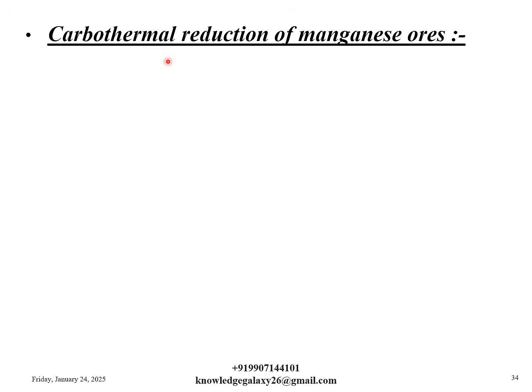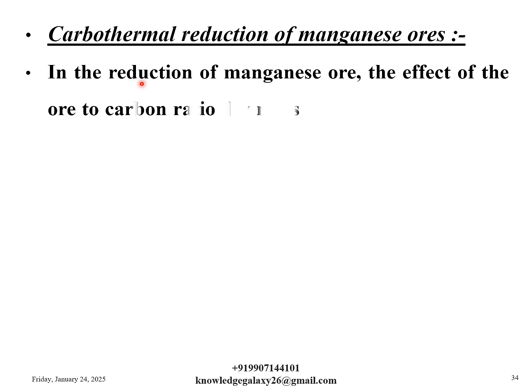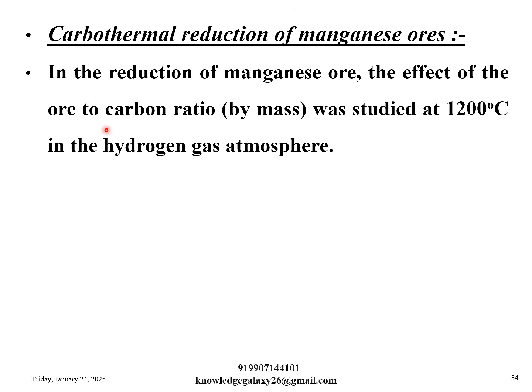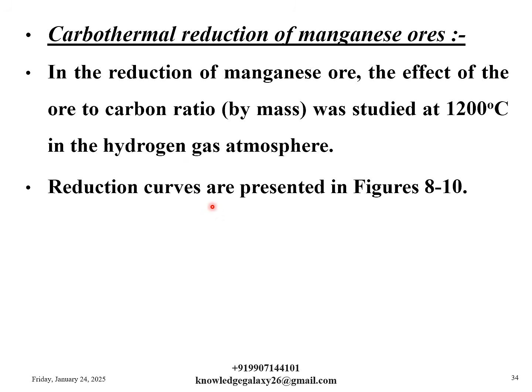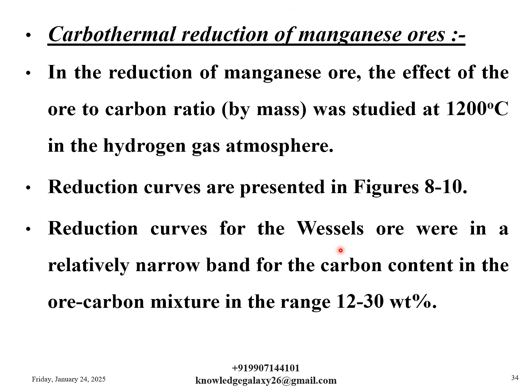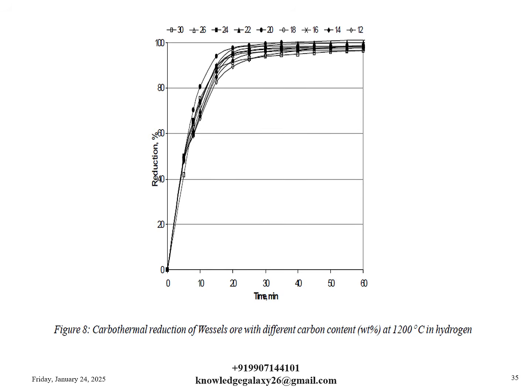Now, next step is carbothermal reduction of manganese ores. In the reduction of manganese ores, the effect of the ore to carbon ratio by mass was studied at 1200 degrees Celsius in the hydrogen gas atmosphere. Reduction curves are presented in figures 8 to 10 in coming slides. Reduction curves for the Wessels ore were in a relatively narrow band for the carbon content in the ore carbon mixture in the range of 12 to 30 weight percentage. So this is figure 8, which shows the carbothermal reduction of Wessels ore with different carbon content, that is in weight percentage, at 1200 degrees Celsius in hydrogen.